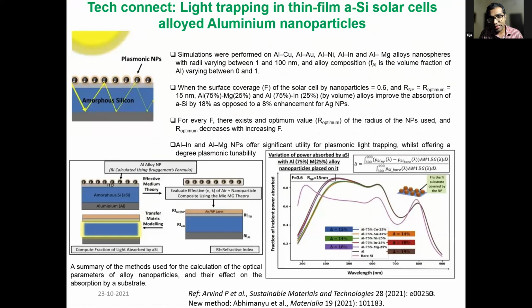So that is not yet all. It turns out that simulating those core shell nanoparticle structures can actually be very difficult. So what we did in between was we developed our own algorithm for being able to map a core shell particle to a homogeneous particle computationally. And then what we have been doing is we have been placing it on top of semiconductor slabs and seeing how these semiconductor slabs will start absorbing light in a more efficient manner.